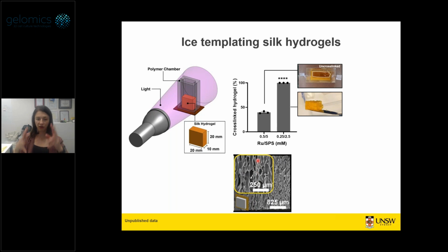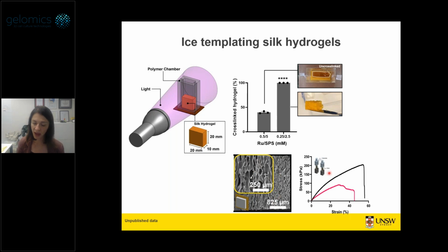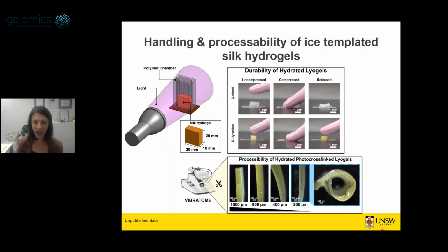And we can ice template these, right? So we can now unidirectionally freeze these hydrogels, and we get alignment in our pores and interconnected pores. And we know we have anisotropy in mechanical properties. So depending on whether we pull in one direction with the pores or against the pores, we get different mechanical properties, telling us that we do have this inherent anisotropy in our materials. And these retain the inherent properties of their original hydrogels, right? Where these are now ice templated, and the ones that were beta sheet cross-linked actually are still brittle and difficult to handle, but the ones that are dityrosine cross-linked and now have porosity introduced into them are actually really easy to handle, quite elastomeric.